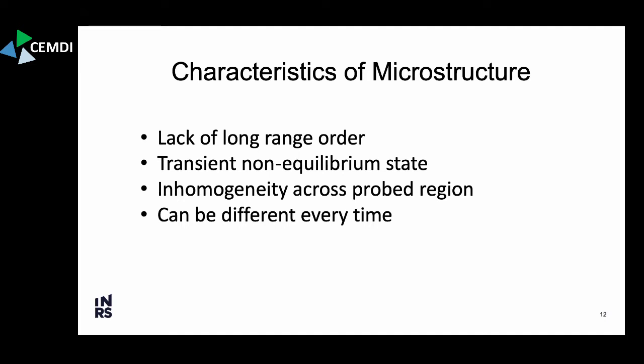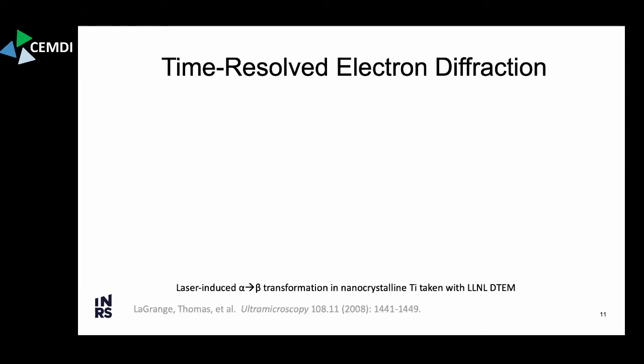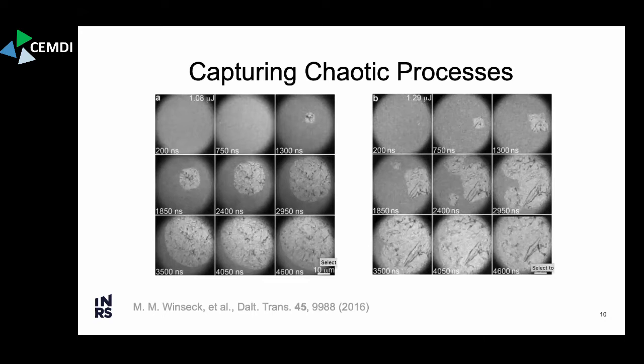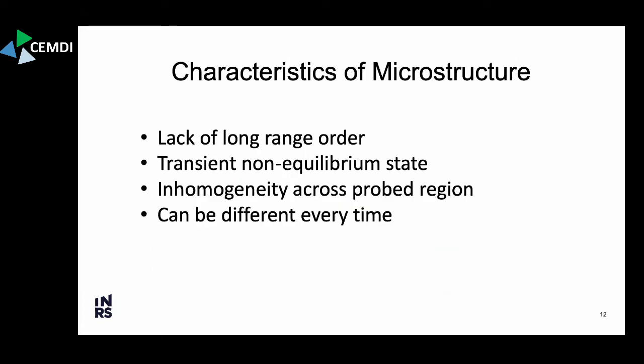the characteristics of the material and the microstructure that you're going to be analyzing at each time point don't have very long range order. It's rather transient and in a non-equilibrium state, so you can't apply your traditional expectation of what the structure of the material might be. It's inhomogeneous across the probe region, perhaps. If we're probing the diffraction pattern from an entire region here, you're getting a mixture of both amorphous and crystalline contributions, and it's different in every shot. So this poses a challenge to the analysis of this diffraction data.